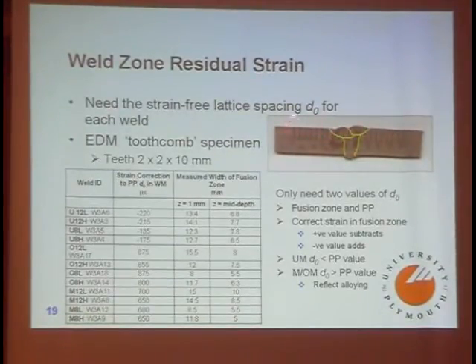But what we're interested in is we then can electro-discharge machine these little teeth in it. And the idea is that we've got a thin slice, we've got separate teeth. If you measure along these teeth right at the end, in principle, you should have a residual stress-free piece of material. And we're trying to identify how the strain-free lattice spacing varies from the parent plate to the fusion zone. And these yellow lines roughly indicate the fusion zone on that specimen.